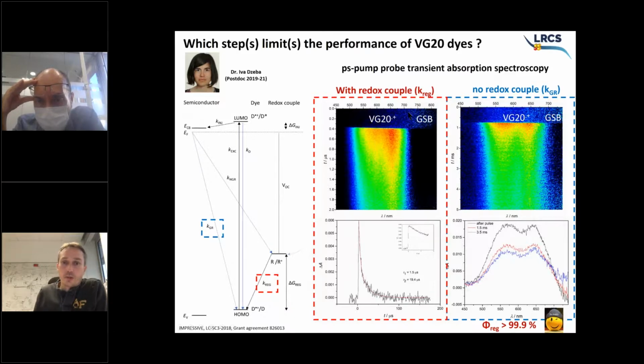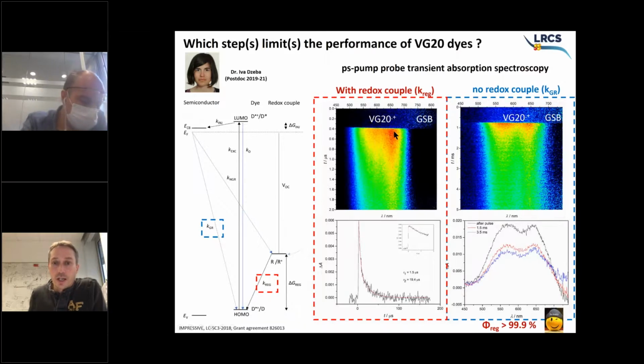So we have a very nice setup with a streak camera, which affords, first, when you include the redox couple in the electrolyte, to see at which speed the hole from the radical cation is transferred to the redox couple. This is the spectral fingerprint of the radical cation, and this is how fast it is all transferred to the redox couple. And here you have the ground state bleaching, which means that the ground state is not absorbing anymore because it is oxidized already.